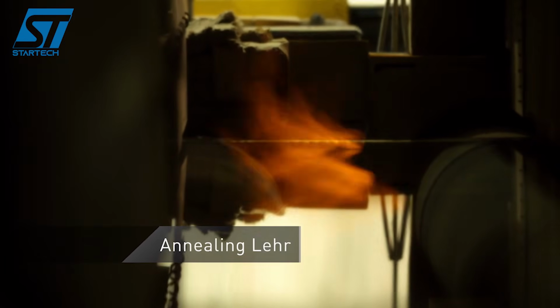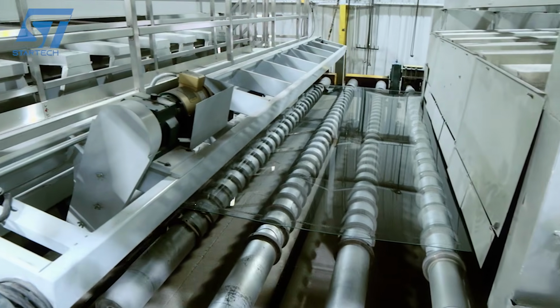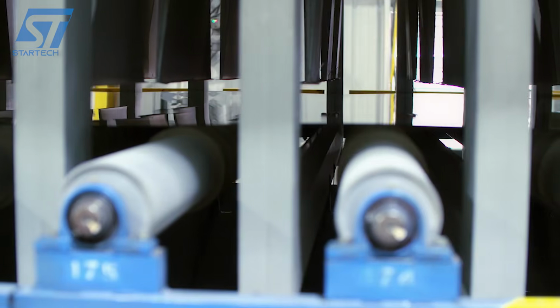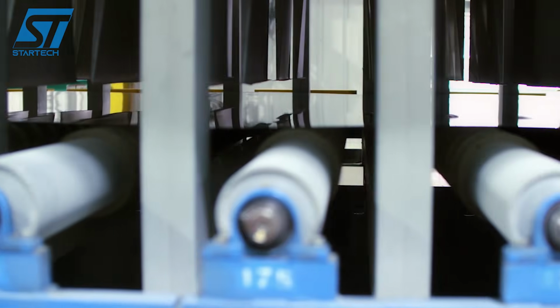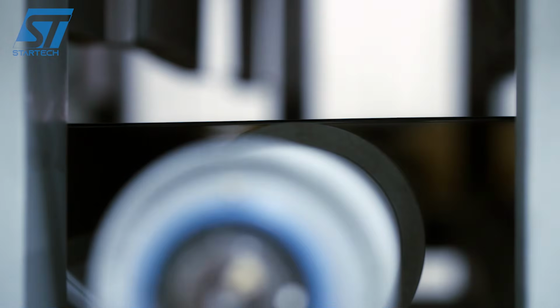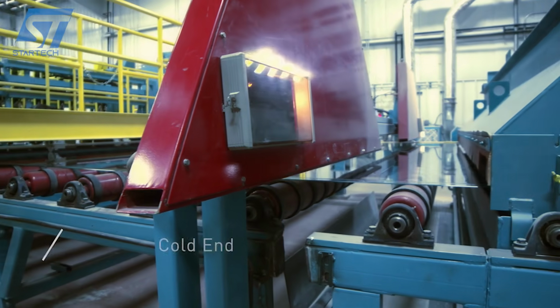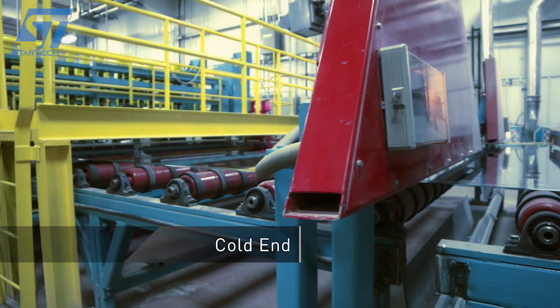consumption. This carefully blended batch feeds into a massive continuous furnace, stretching over 160 feet long and running at temperatures approaching 1600 degrees Celsius, nearly 3000 degrees Fahrenheit. The raw materials melt together into a homogeneous molten glass river, flowing at a carefully controlled rate. Now comes the magic of the float process.